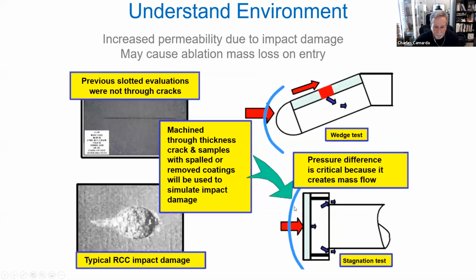And so what we learned from that was that the way we had been testing this material, if you look on the bottom, was 90 degrees to the flow. Okay, we thought that was the worst case. Once we learned that flow at an angle was a much worse case, we started to change the way we tested, right? So we have small coupons of this material.